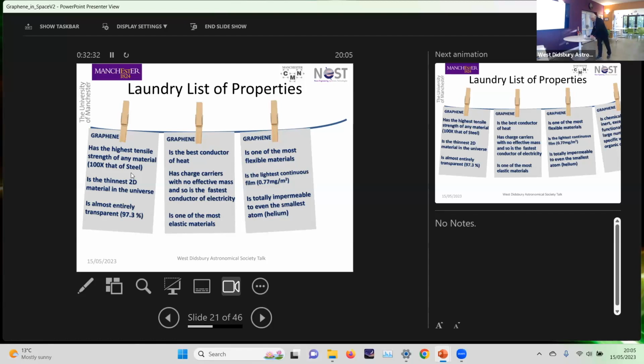Interestingly, though, it's immensely flexible when it's free, but if you clamp two edges, it becomes incredibly stiff. It took us a long time to work that one out because we found that we could suspend a flake of graphene in space for quite a long way, and yet when you had it over a hole or something, you could bend it really easily. So we tried to work out why that was, and it turned out it depends on how you clamp the edges. If you let the edges be free, then it's flexible. You can bend it easily. But if you clamp them down, then it becomes very stiff. What we'd done is we'd put this flake out into space, and we'd coated the surrounding area with gold. So it was actually clamped around the edges.